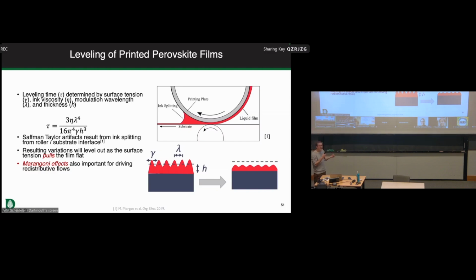The fluid phenomena that we're fighting are essentially the tendency for films, when you pull them apart, to form this Saffman-Taylor defect. So if you have 2 different fluids, air and the ink in this case, with vastly different viscosities, there's this phenomenon that you can observe, for example, if you peel 2 sheets apart, where they form these viscous fingers. And these viscous fingers, it turns out, are the biggest challenge for us in printing solar cells, to be able to make that uniform thickness of the solar absorber.